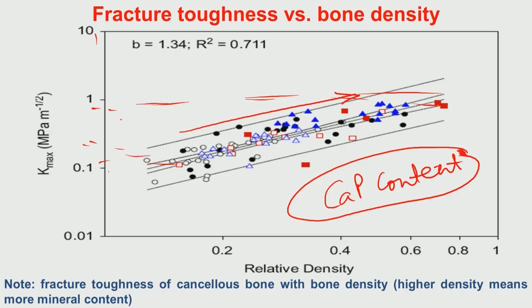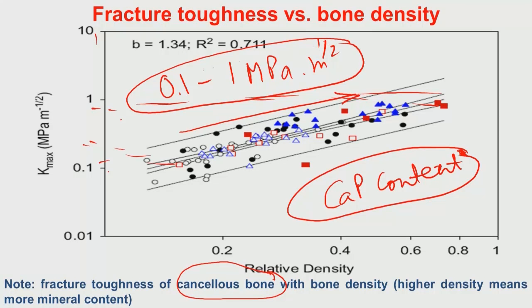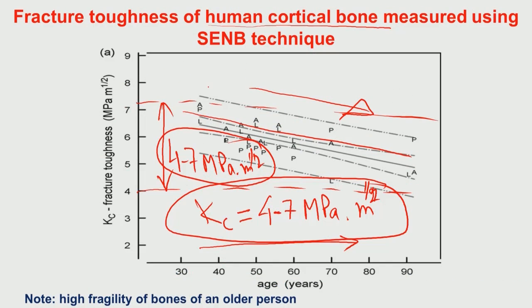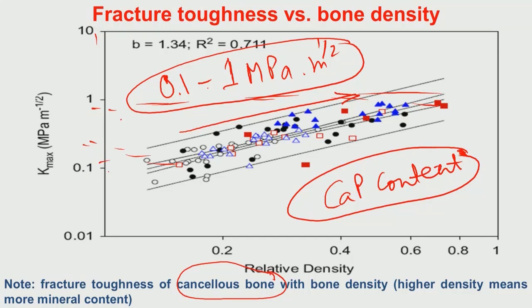So, this is typically the cancellous bone structure. Cancellous bone is much weaker. Cortical bone has a fracture toughness between 4 and 7, whereas cancellous bone has a fracture toughness between 0.1 to 1 MPa square root meter. So, essentially cancellous bone is extremely weak as far as the mechanical property is concerned, and therefore it has an extremely low fracture toughness. It is extremely fragile as far as mechanical loading is concerned. So, these two bones, cortical bone and cancellous bone, have widely different fracture resistance properties in terms of fracture toughness.